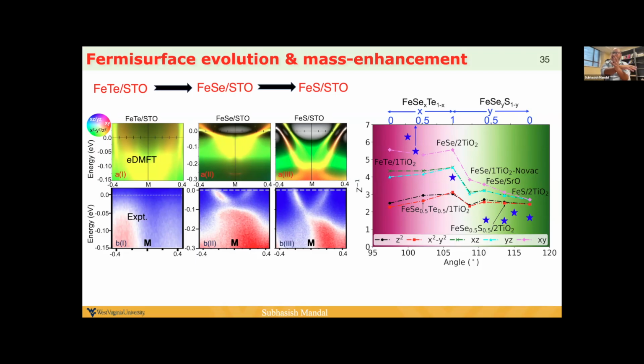I've talked with many experimental colleagues there. If it's a single layer film, it actually goes to the STO lattice parameter. So the lattice parameter is different, and the angle is also different. The cost of going from bulk to on top of STO is the reason for the change here.